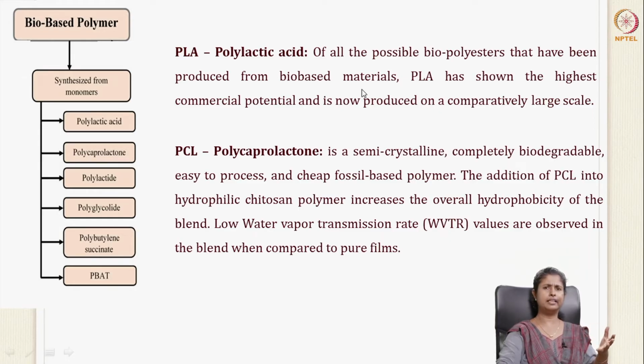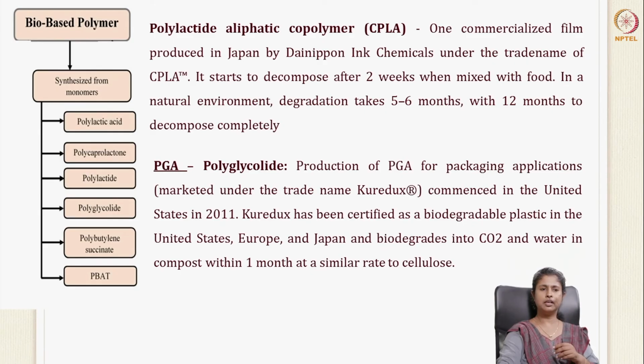If you look at any biodegradable plastic bags that you purchase in the market, one of the ingredients will always be polylactic acid. It's very much in use commercially. The second one is PCL, which is polycaprolactone. This is a semi-crystalline, completely biodegradable, easy to process and cheap fossil-based polymer. If you add this PCL into hydrophilic chitosan polymers, it will increase the hydrophobicity of the blend, and a low water vapor transmission rate value was observed when you formed films adding this PCL into it. It's another important monomer that you can add in your bio-based polymer.